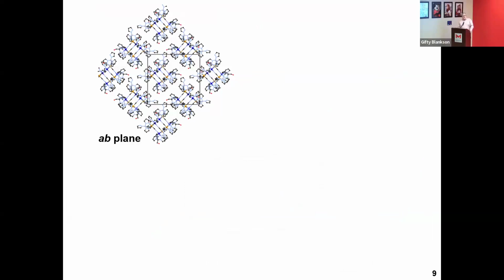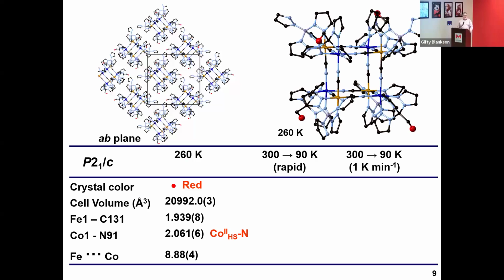A better view is showing it like that. Again, the void space between those clusters is solvents and anions. Summarizing a lot of work, we showed at high temperature, near room temperature, it was red. We have rather long cobalt-nitrogen distances that are reflective of this cobalt(II) high spin. If we quickly cool it, we haven't given it enough time to relax, so we've trapped most of the electrons in the high temperature state. And lo and behold, it still looks red.